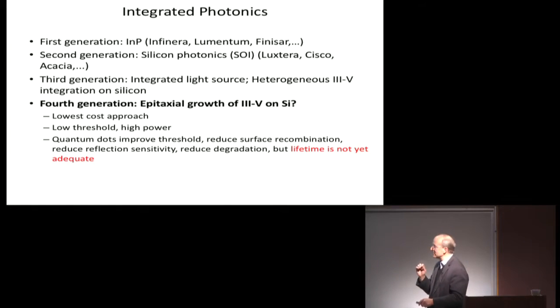We're using quantum dots. So the advantage of quantum dots is lower threshold and high power, as you'll see. And that's, again, the big advantage of quantum dots is that they reduce the threshold. They reduce surface recombination, and that's important. So HP in particular is making very small devices, and the surface recombination of those would be much worse if they weren't using quantum dots. So their approach is entirely using quantum dots. You also reduce reflection sensitivity. So again, that Luxtera module you saw had an isolator in there. Okay, why does anybody else need an isolator? Well, if you have a quantum dot, it should be significantly less sensitive, which isn't obvious, but I'll show why in a second. And then the final reason is to improve the degradation.